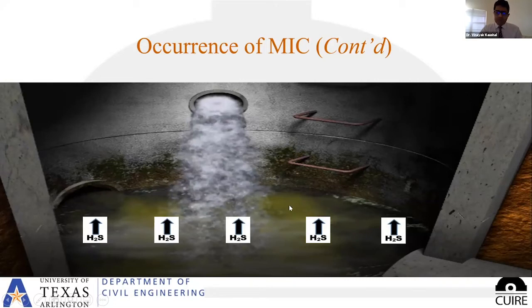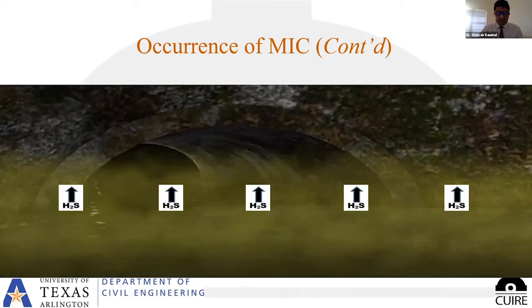Basically, you can see the flow here, and also at the same time there is turbulence, such as force mains, and also the drop structure is basically introduced, right? So then we can see the release also from the laminar flows, right? The wastewater is going through different hydraulic structures on its way. And when the dissolved hydrogen sulfide concentrations become elevated due to the prolonged retention time, so as the time increases, there is an increase in the concentration of hydrogen sulfide, because this is a continuous process and this keeps on happening with the passage of time.